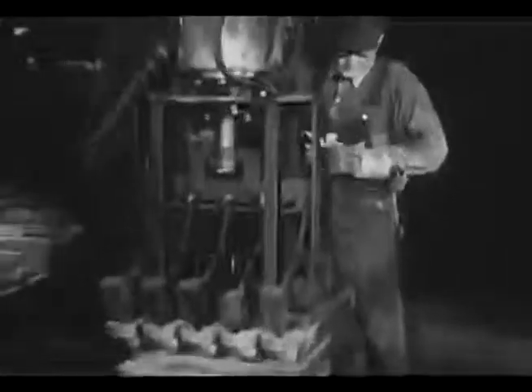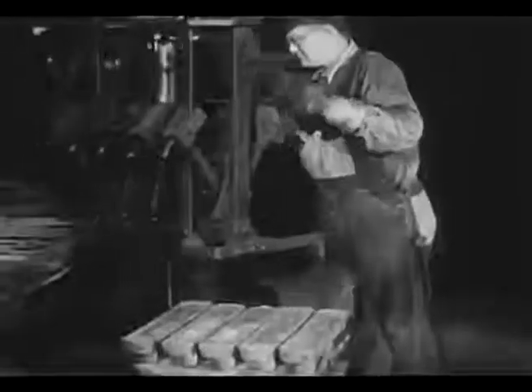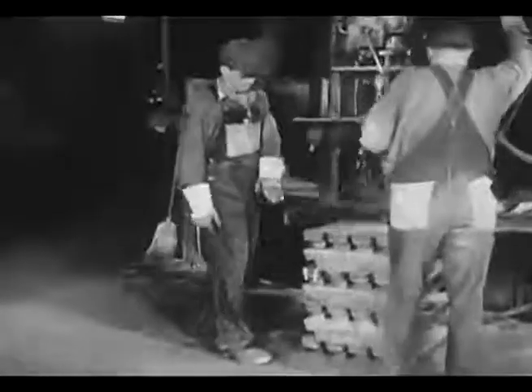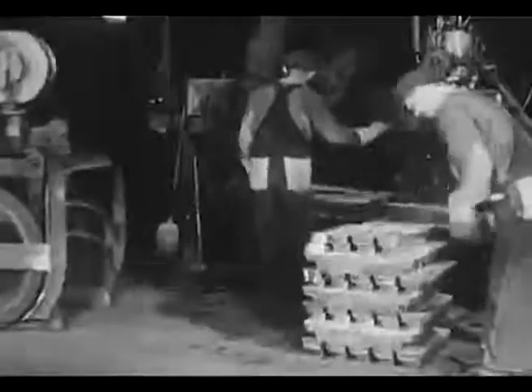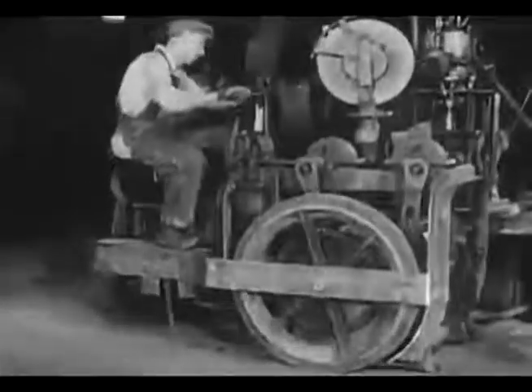The filled molds pass through a continuous spray of cold water applied at top and bottom to cool the lead. An automatic marking device stamps the identification number on each pig. Five at a time, the 100-pound pigs are plucked from the casting wheel by a compressed-air device, swung around, and stacked in piles seven high. The lead pigs are cast with protruding ears to facilitate handling. An electrically operated buggy picks up the 3,500-pound stack by the ears, transports them to the weighing scales, and then delivers the metal to freight cars on the refinery siding.